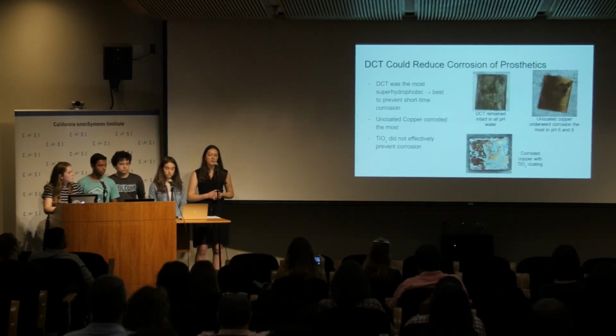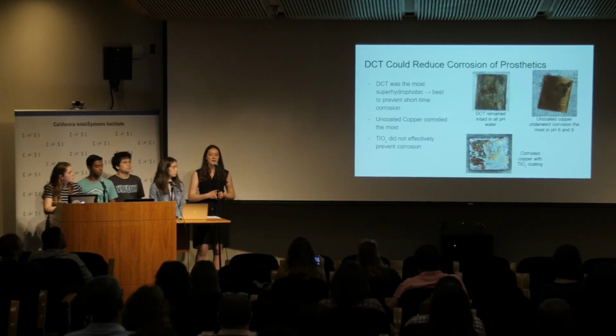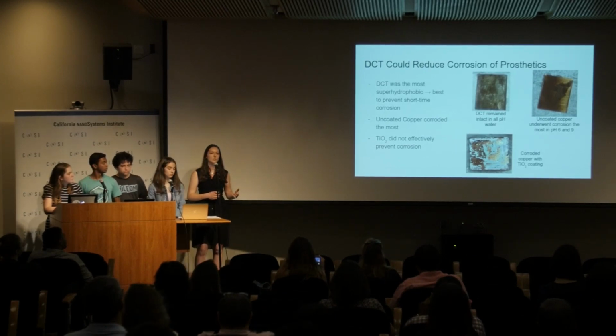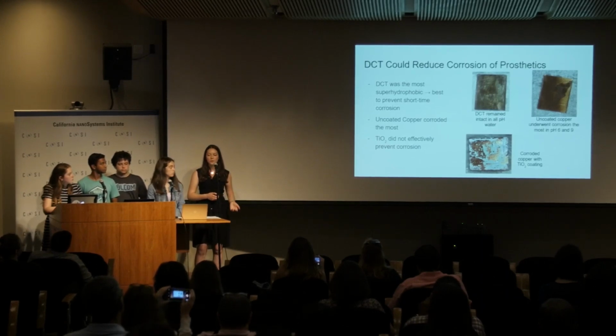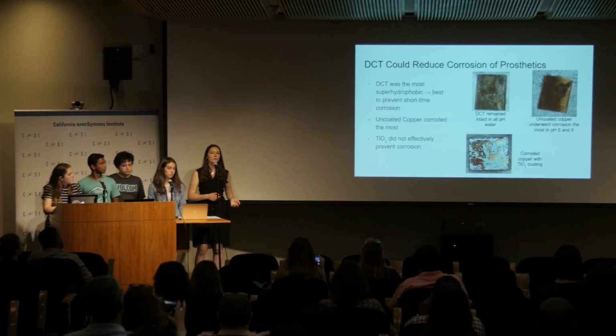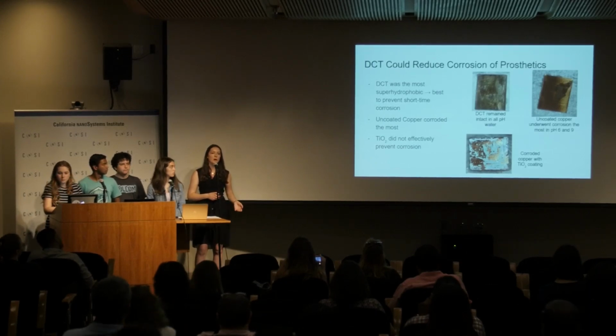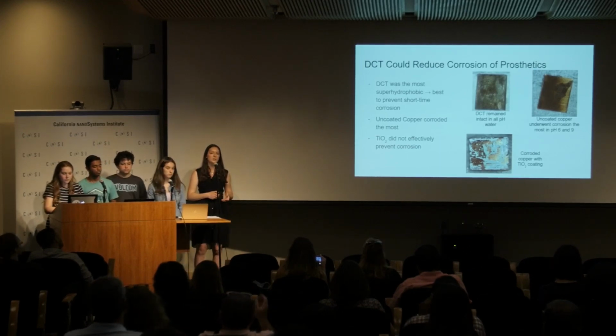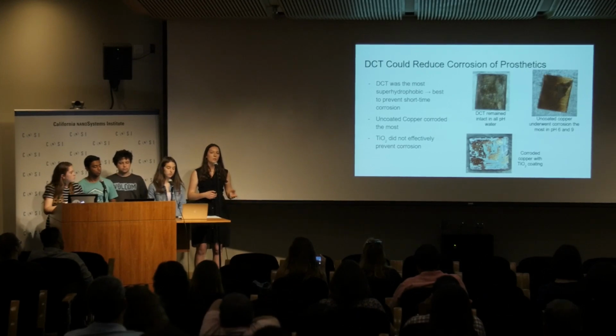So we concluded that DCT was the best coating to reduce the corrosion of prosthetics, and we came up with that conclusion because DCT was the most super hydrophobic, and so it was the best to prevent short-time corrosion. But we also concluded that uncoated copper was the one that corroded the most at pH 6, which we originally thought was pH 5, but when we look at the loss of superhydrophobicity, it was actually at pH 5, so we can say that our hypothesis is partially correct.